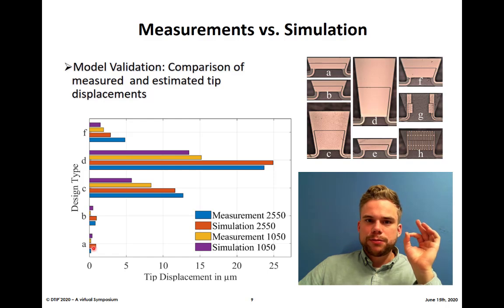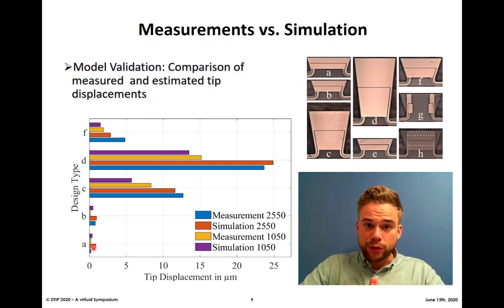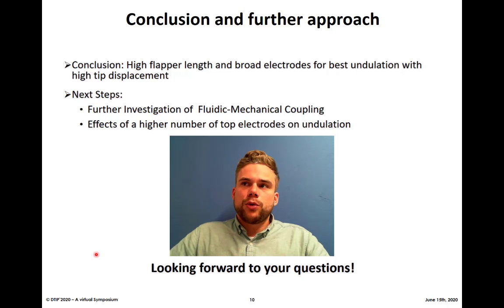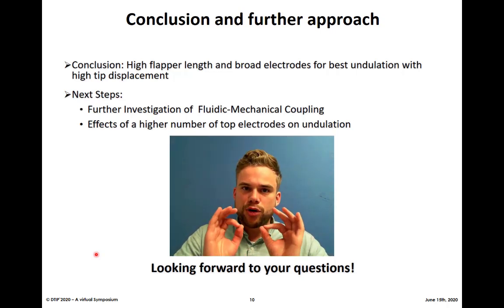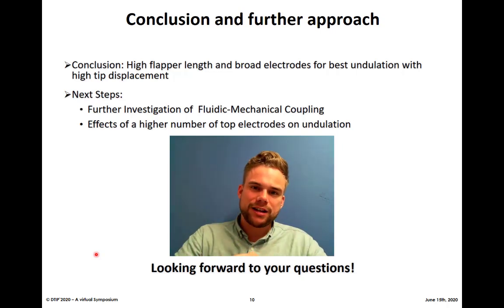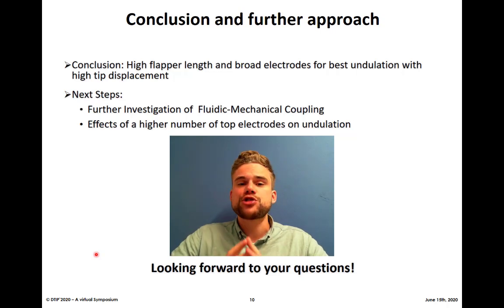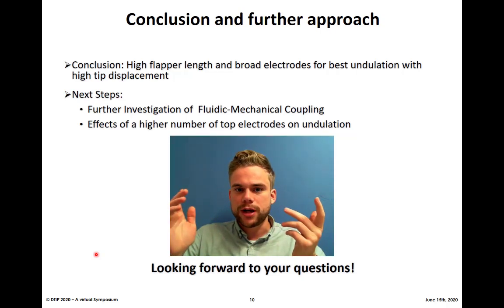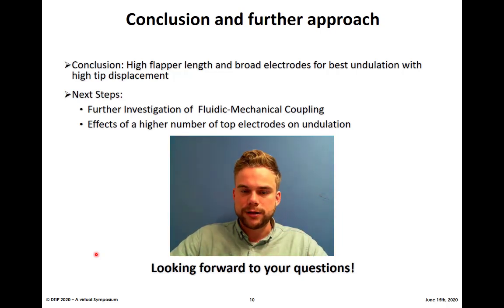Our explanation for that might be that we don't have a complete bidirectional coupled fluid-structure interaction, and our approximation with the velocity-dependent damping force comes to a limit here. So this might be an explanation that this approximation works better for large flappers. Okay, so our conclusion is that the most promising designs exhibit a high distal flapper length and broad electrodes, which was design D. Unfortunately, in that case, we have a limit in robustness, right? Because the longer the flapper gets, the less robust it will be in the case that it's moving fast or it's subject to vibration.